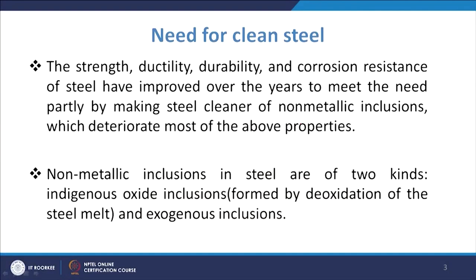Our effort targets inclusions because mechanisms exist to filter out larger-size inclusions, but the critical size that must be removed is becoming smaller and smaller. Properties like strength, ductility, durability, and corrosion resistance are all impaired by non-metallic inclusions. Making steel cleaner of non-metallic inclusions is the key to improving these properties.